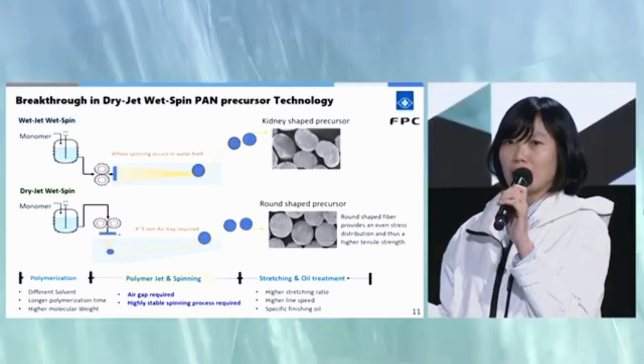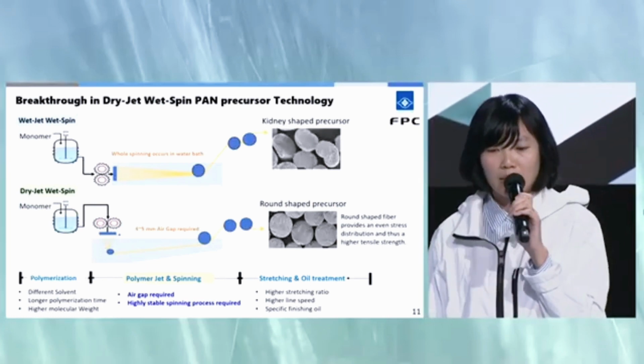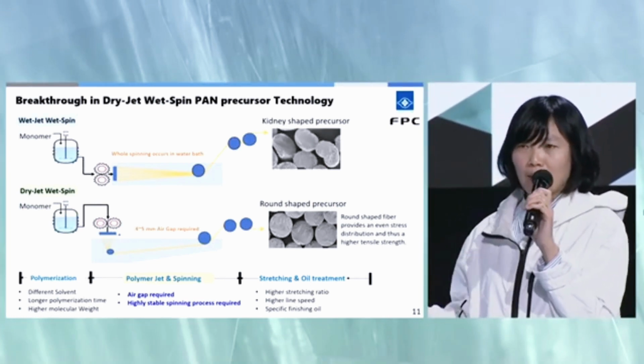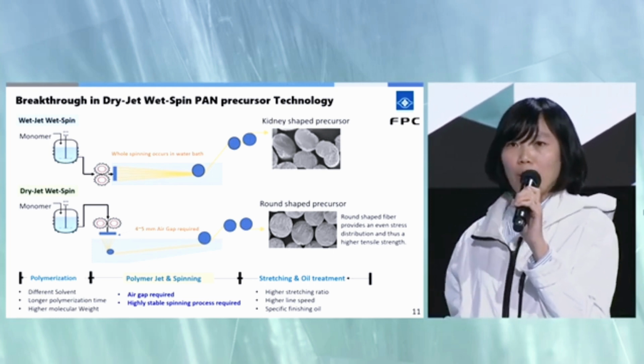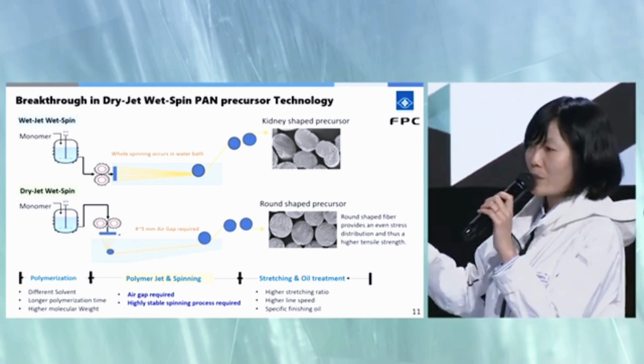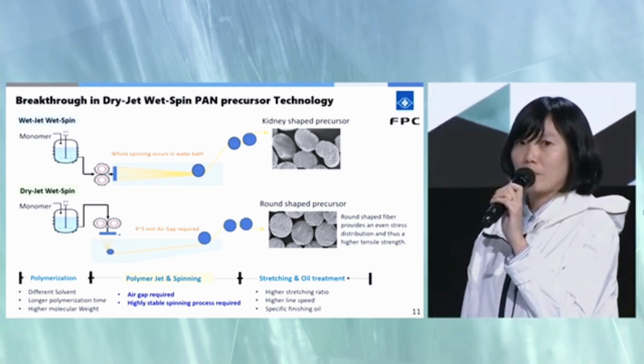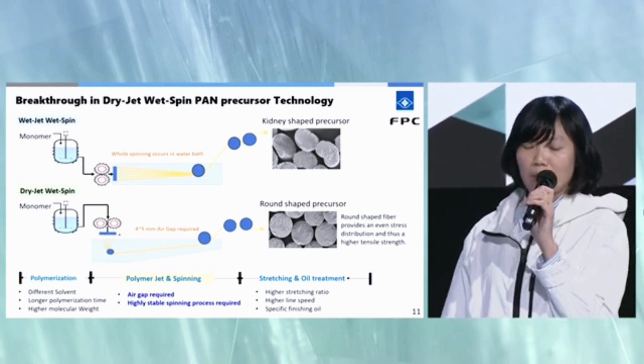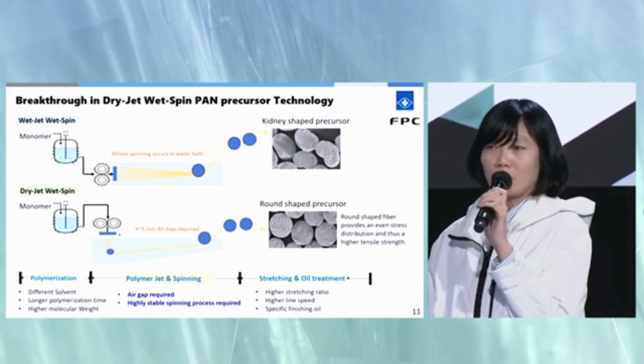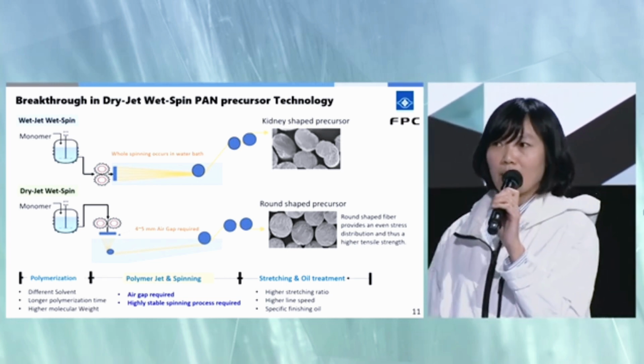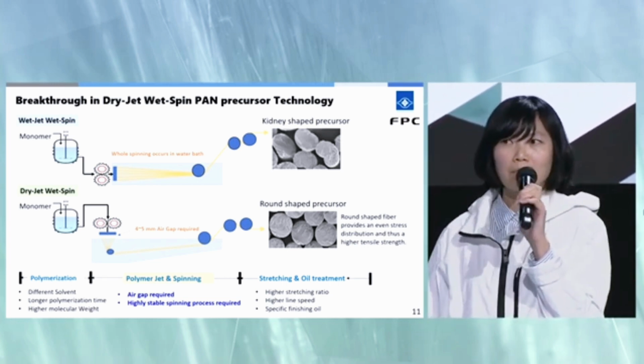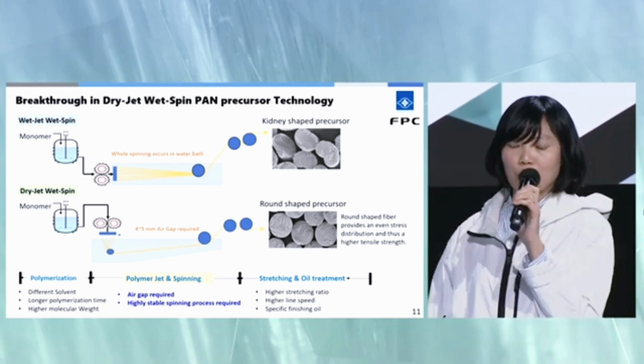So here I want to explain the breakthrough for dry jet wet spinning. Maybe some people don't know the difference between dry jet and wet jet. In the past, our carbon fiber was mainly from wet jet. The top one is the illustration of the wet spinning process. You can see the polymer solution is pumped into the water bath, so the entire spinning process is in the water bath, and the precursor will be kidney shaped.